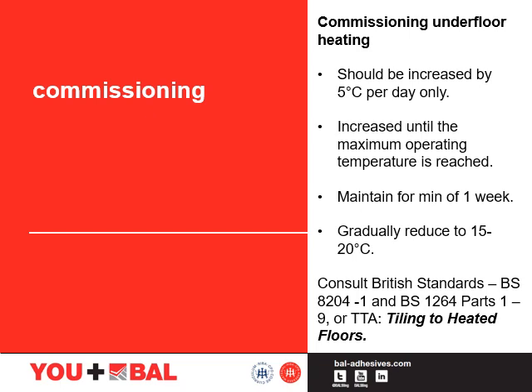It should be increased by 5 degrees per day and also to the maximum operating temperature of the system. Maintain that temperature for a minimum of 1 week and then gradually reduce it by 5 degrees per day to 15 to 20 degrees. We would suggest consulting the British standards and also talking to the heating manufacturer to make sure all procedures are being followed.